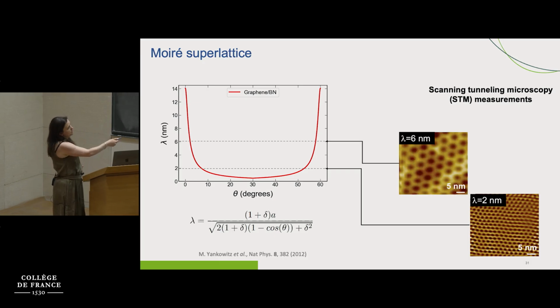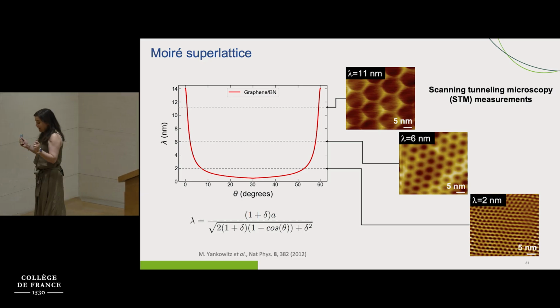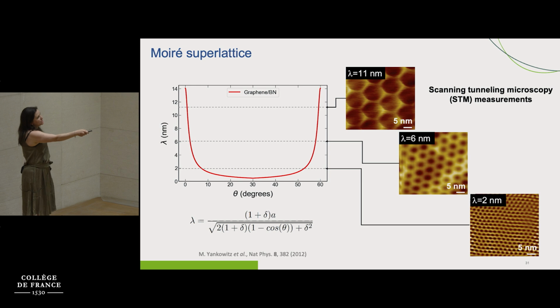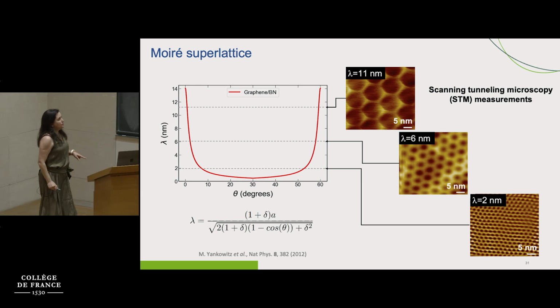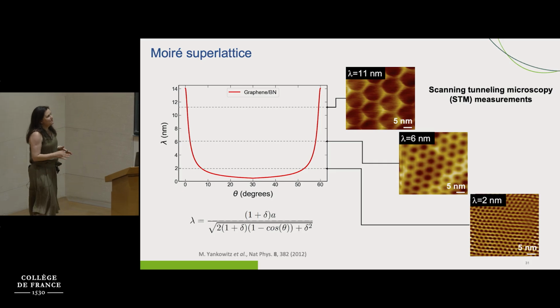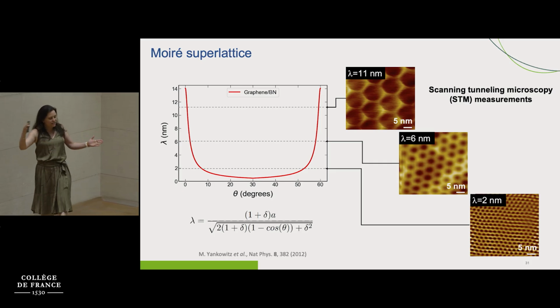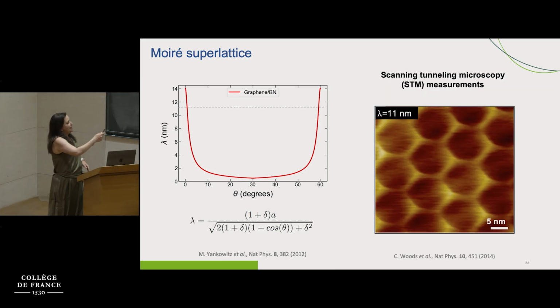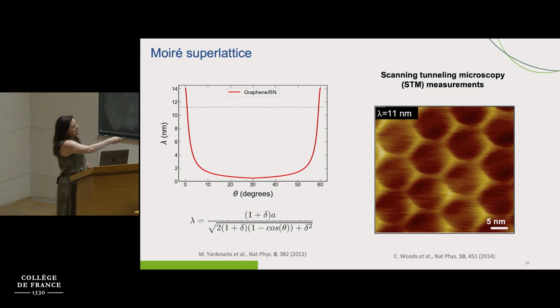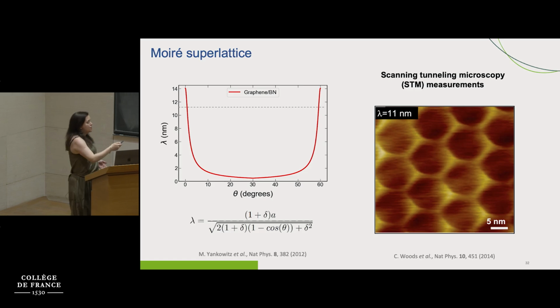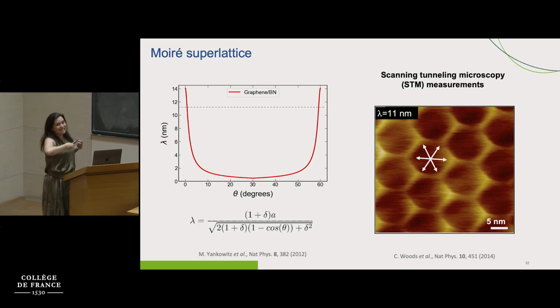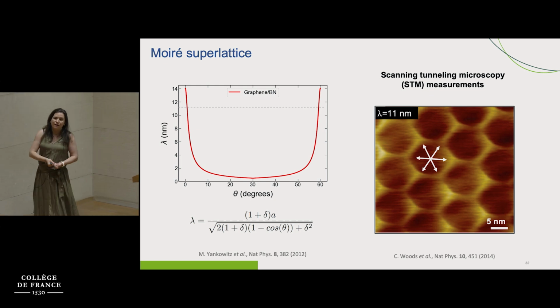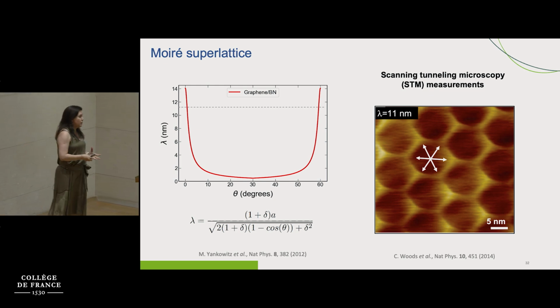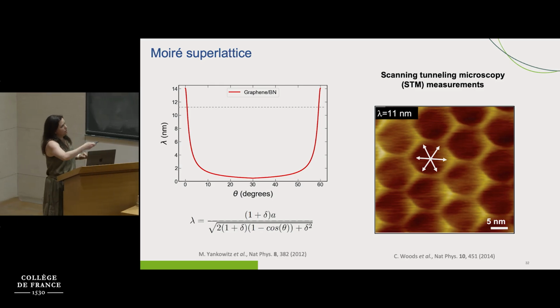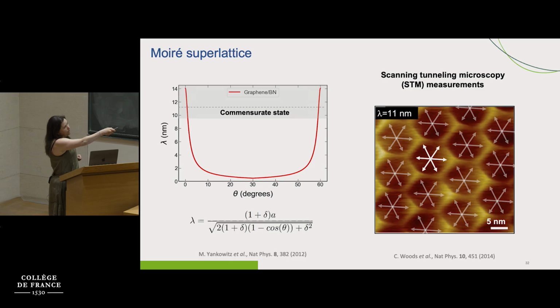So we can see that by changing the angle between the two lattices, we can change the size of this moiré pattern. And very importantly, and I'm unfortunately not going to talk about it, but it's extremely important for experimentalists, theorists, and everyone else, is the fact that for very large superlattices, you are not just going to have a moiré pattern, a periodic potential that is superimposed, but you are also going to have a strain that is developed inside the moiré lattice. This is because it's more favorable for graphene to stretch and match the lattice of boron nitride instead of just staying in its original position. So this strain is going to develop all around.